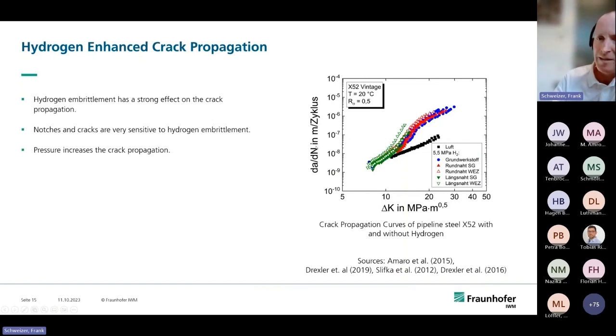This means dN is one cycle. So you take your sample and pull it one time, and the dA is the crack opening which happens due to that. And the more open the crack gets, the more pronounced comes the stress intensity on the lower side. And you see the normal shape of these curves: there's no propagation, then you have a threshold, and then you have a linear relationship with the crack propagation.